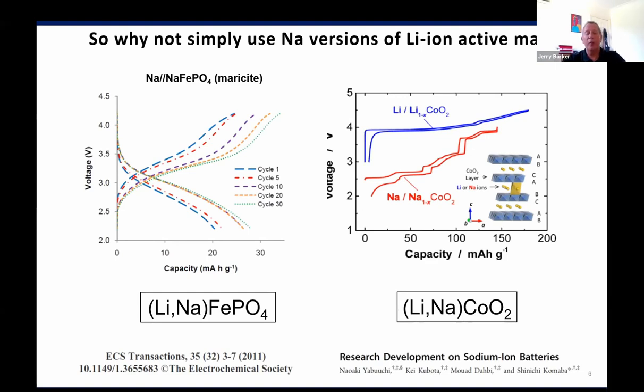If you think of lithium iron phosphate, a super material for lithium ion, if we make the equivalent NaFePO4, fairly straightforward to make, but you get a transposition of the sodium and the iron sites, right? So now the iron is on what would be the lithium site, and the sodium is on what would be the transition metal site. What that means is you end up with fairly low specific capacity. So you'll know lithium iron phosphate in a lithium ion cell can generally run at 150 milliamp hours per gram. NaFePO4 runs in the range of 20 to 30 milliamp hours per gram. Interesting material, but far too low in terms of specific energy.